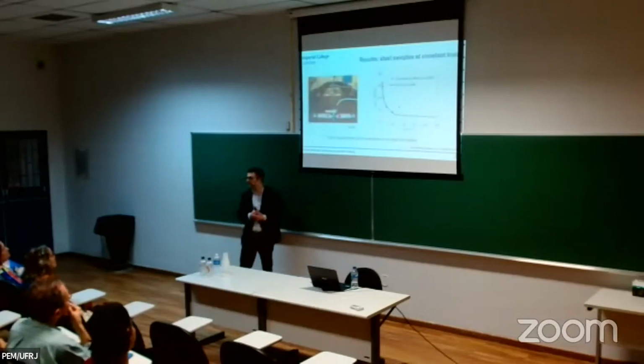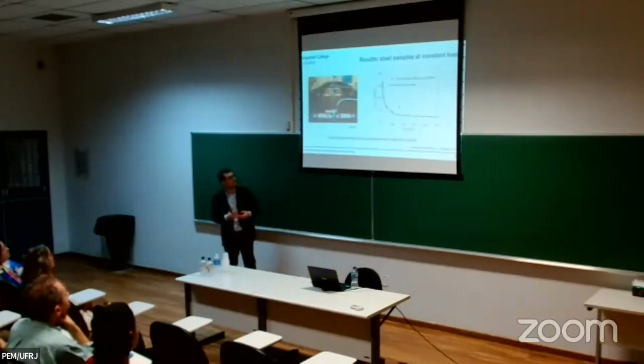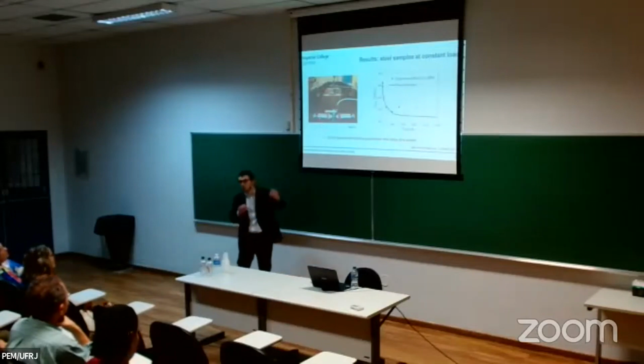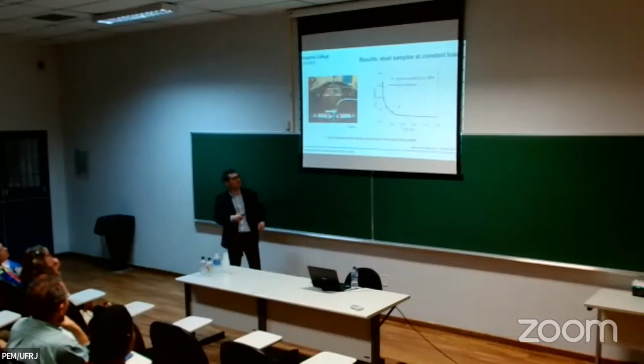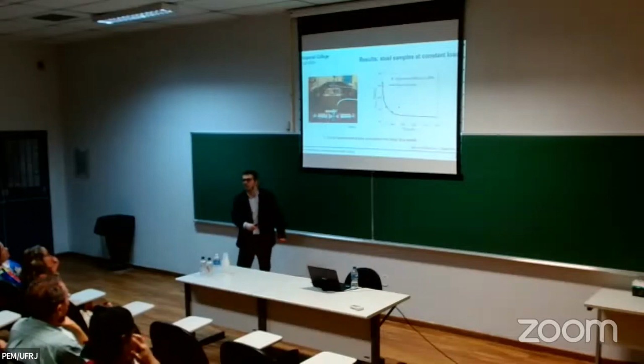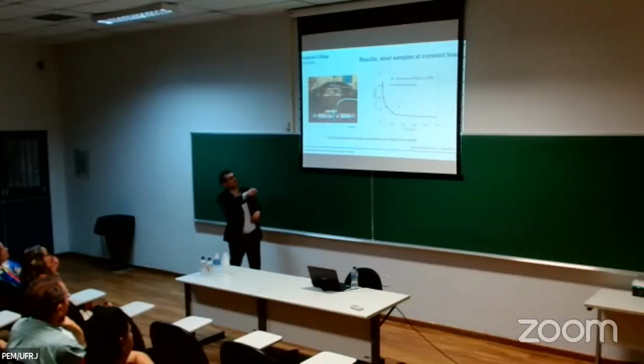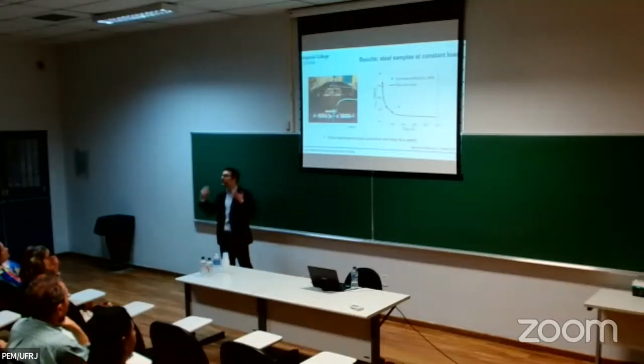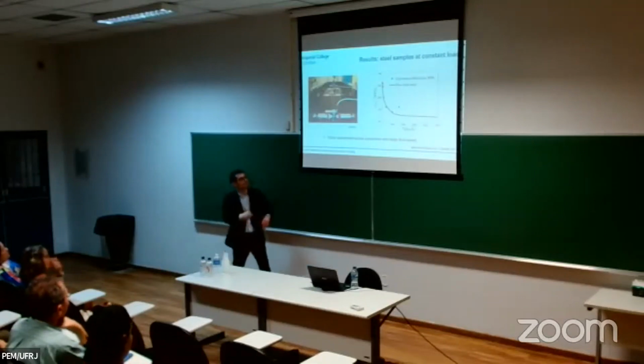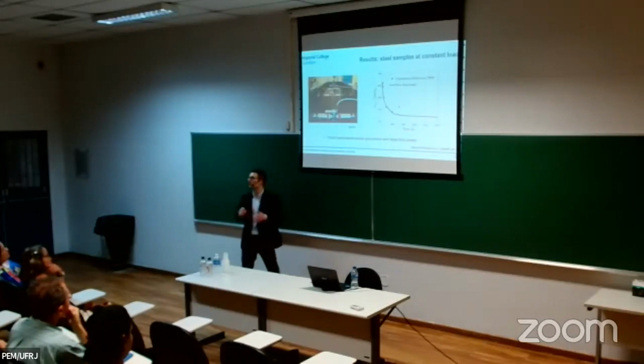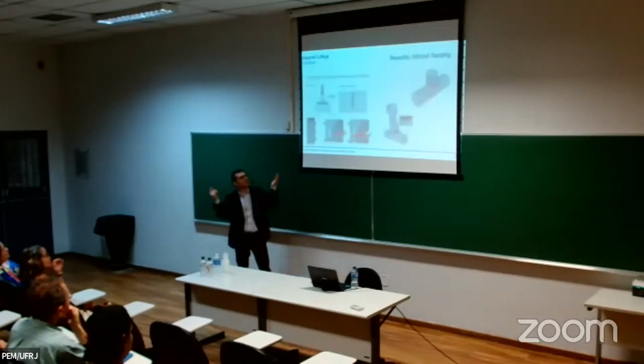And these are a set of more interesting experiments. This was done at SINTEF in Norway. What they did was immerse notched stainless steel samples in a seawater bath. They subjected them to a constant load, each of them at a different load, and measured the failure times. As you can see, what they were hoping is that one of them would remain without failing for quite a long time, but all of them fail relatively early, simple experiments in terms of engineering time scales. But what we can do with our model here is not only reproduce the experiments, but also run virtual experiments over very long time scales so as to determine what is the critical load below which we will not see anything. And essentially, we can do anything we want.